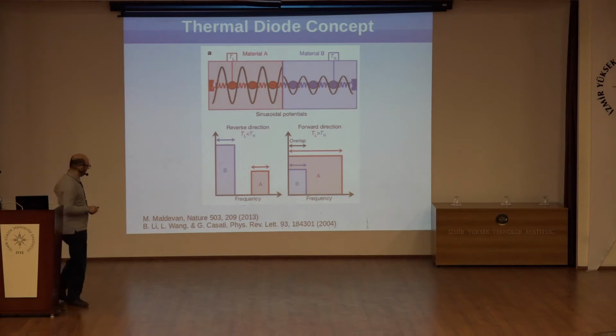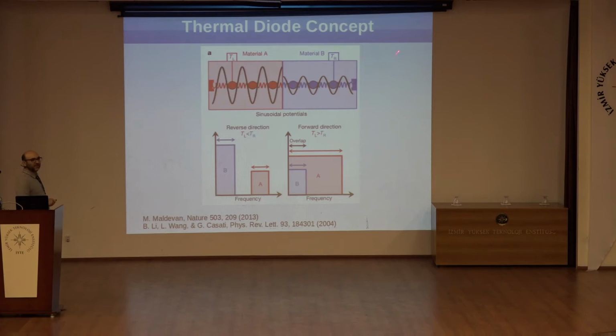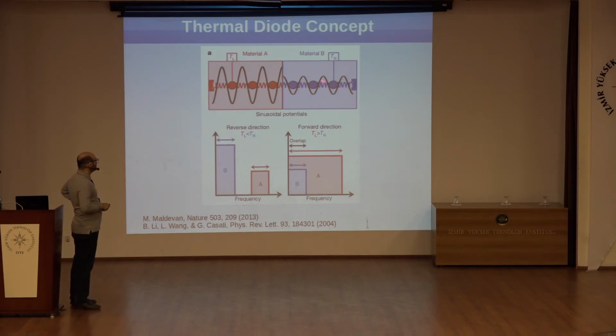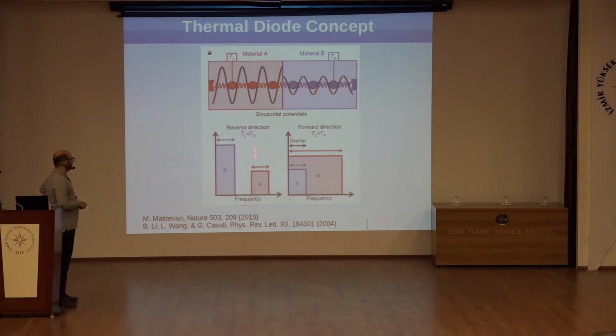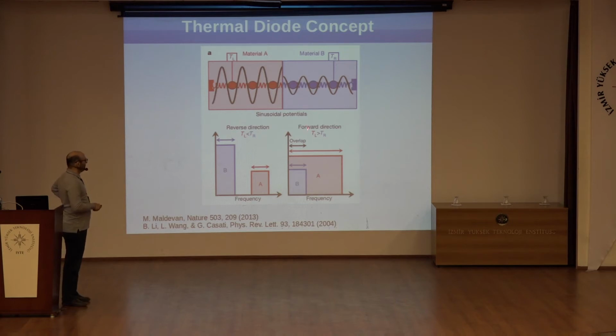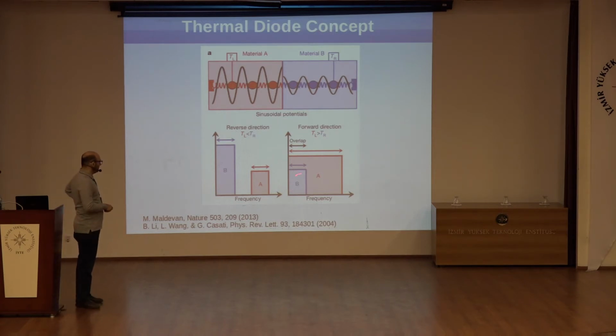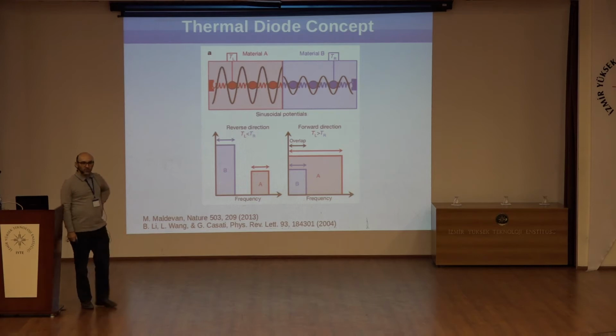an interesting idea. If we have asymmetry in the system, two types of potentials on the two sides of the system, there are different vibrational densities of states at different temperatures, and it leads us to have phonon vibrational density of states mismatch. As you see, when we have forward direction, there is a matched, shared area for vibrational density of states, and in reverse direction there is no shared area.